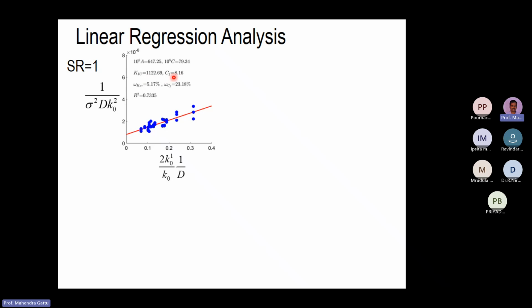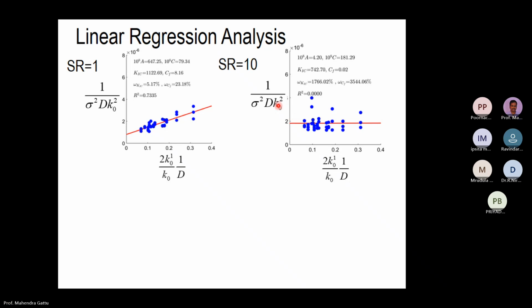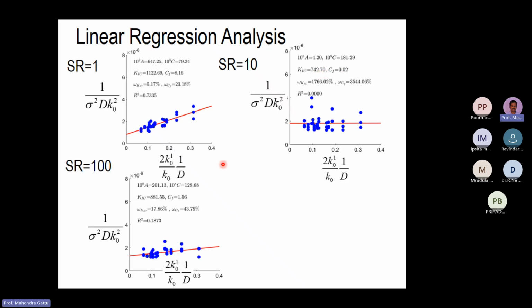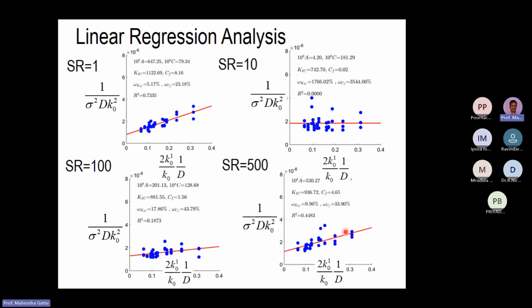Okay, CF is coming around 8.16 and KIC 1122.69. So this is for a loading rate of 1 millimeter per minute, the displacement loading rate. And for displacement loading of 10, we're getting data like this. So the CF value is going to almost 0, and KIC we're getting a lesser value, 742. For loading rate 100, we're getting this trend, and loading rate 500, we're getting this trend.